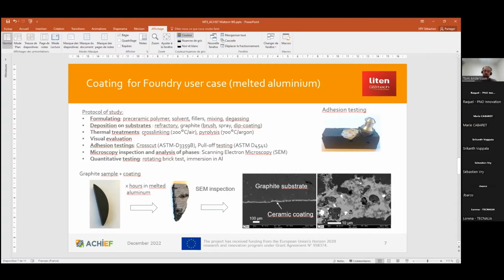The first step is to cross-link the pre-ceramic polymer, and the second step is the pyrolysis at high temperature to convert the pre-ceramic polymer into a ceramic. To assess the performance of the coating, multiple tests are done, like adhesion testing by crosscut or pull-off testing. Microscopy analysis is also performed to assess the integrity of the coating, its thickness, and the presence of defects. This analysis is also done after the samples are immersed into melted aluminum by using a rotating device.